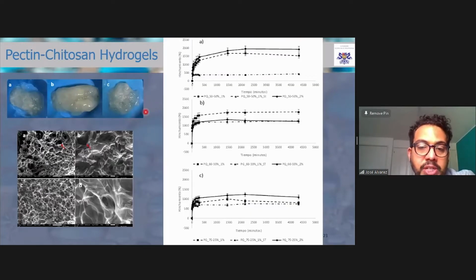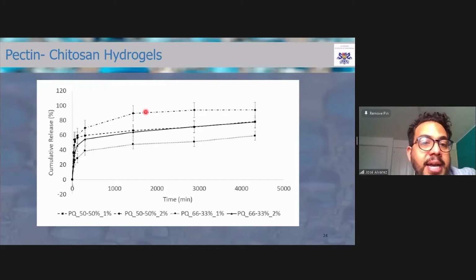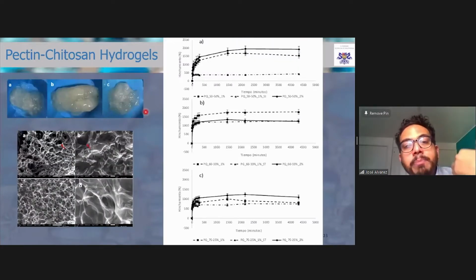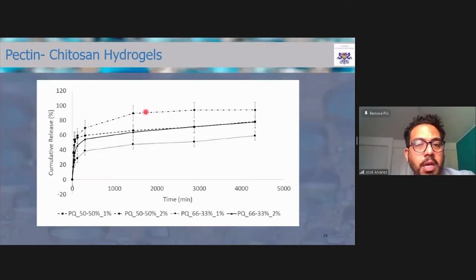And we also saw very important differences in swelling. I'm not going to go into much detail here. And in the release, interestingly, when we have more pectin, the hydrogels were able to swell less. And that also had an influence on the release of acetaminophen.